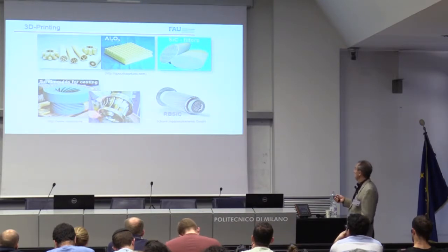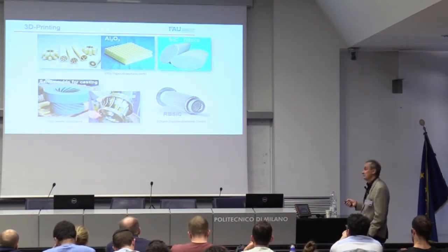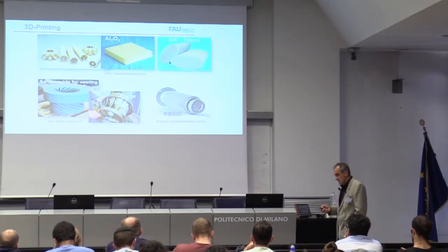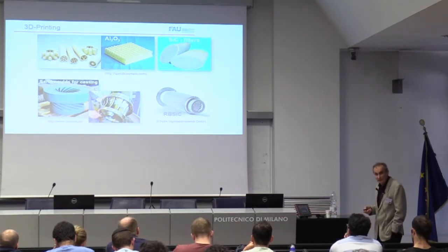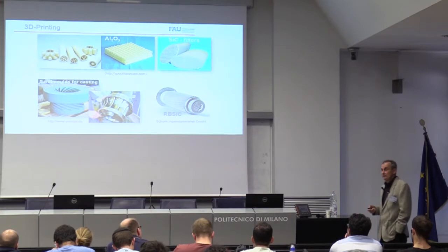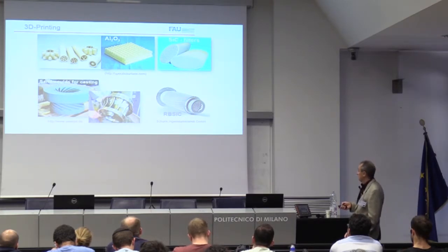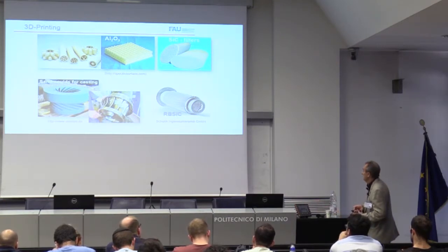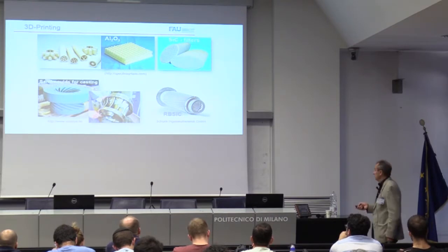And look, you can work also with silicon carbide. Silicon carbide is not easy to work with because the system has a very high melting temperature. But I didn't propose to make melting. It's enough to make a temperature treatment after printing. And of course, you can maybe use some flux material between grains and so on, to make a strong and mechanically stable system.